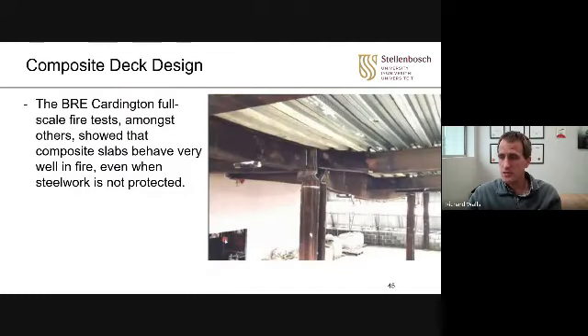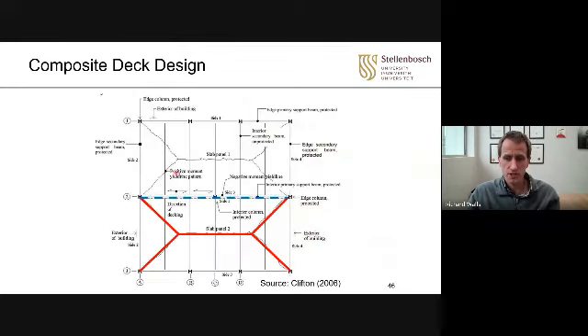You can also design composite decks. For instance, as I said, a composite deck is steel columns, steel beams, concrete floor on top. The BRE Cardington full-scale tests, amongst others, showed that composite slabs behave very well in fire, even when steelwork is not protected. And what you do to design these systems is that, for instance, this is a plan view of a building. You protect your perimeter beams, and then you just allow the beams between to fail.